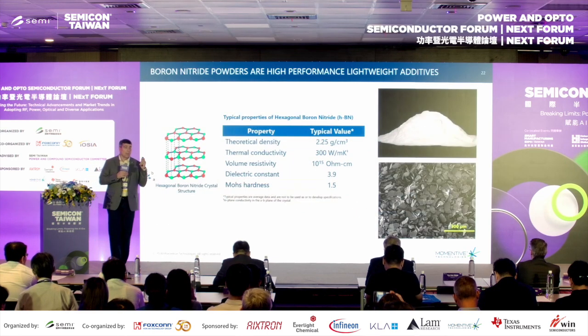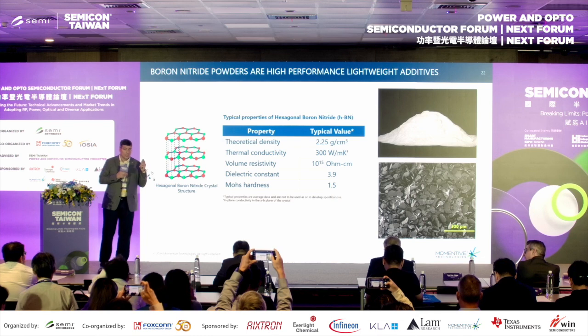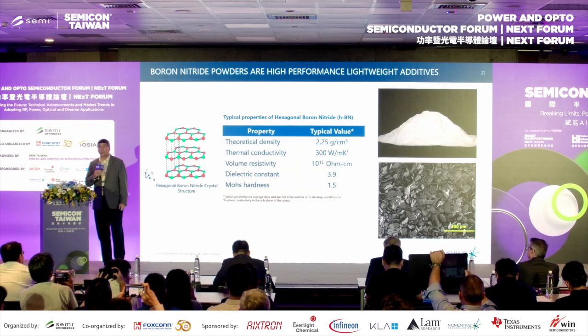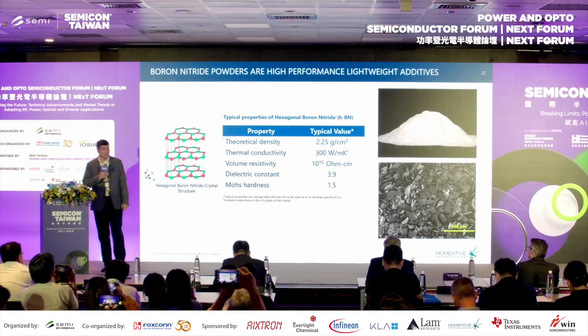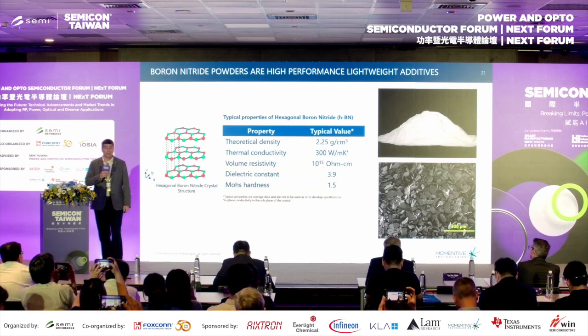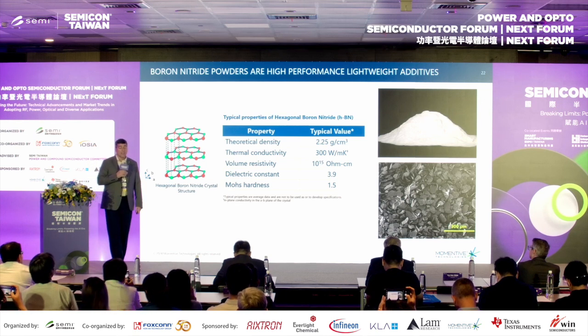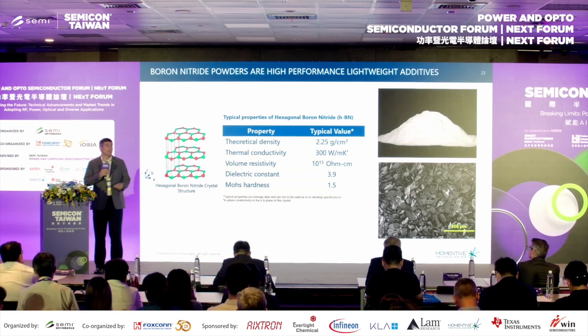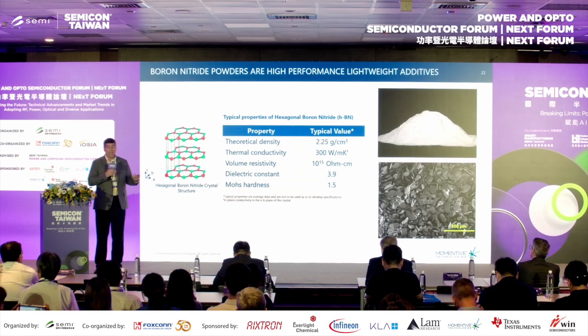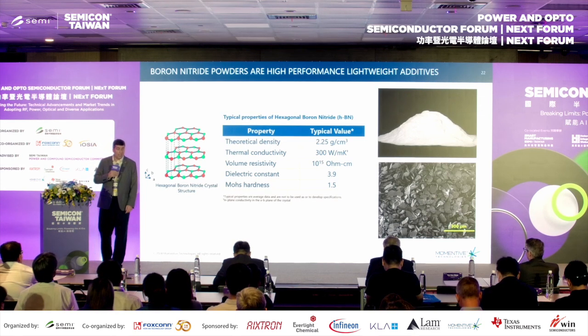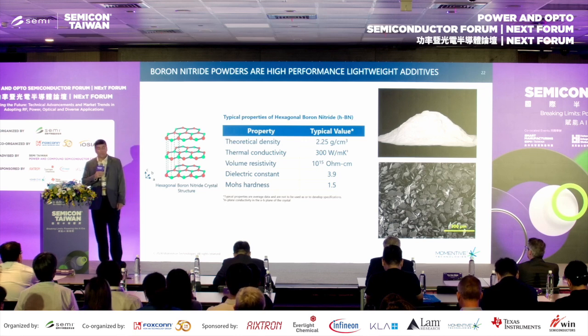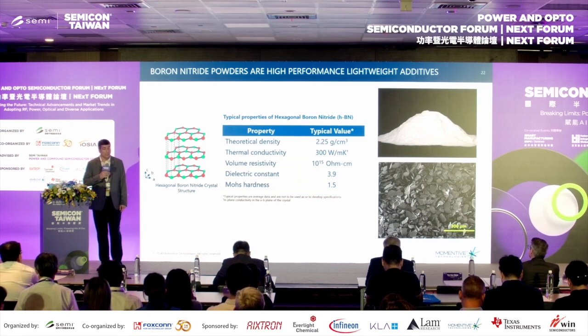So here's some of the typical properties of our BNs. If you notice, it's a fairly lightweight material, right? 2.2 grams per cc, and that's its true value, not the bulk density. Thermal conductivity of 300 watts per meter Kelvin. Again, as I mentioned, just like the PBN, graphite, those other ones, this is a high thermal conductivity material. Volume resistivity, again, fortunately out of pure DI water, at 10 to the 15th ohm-centimeters.